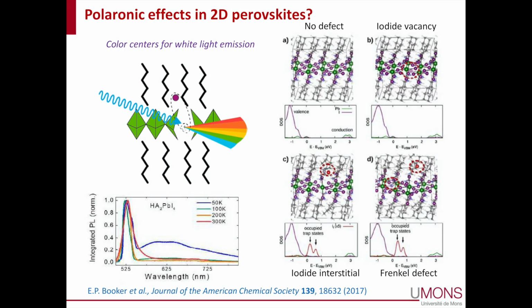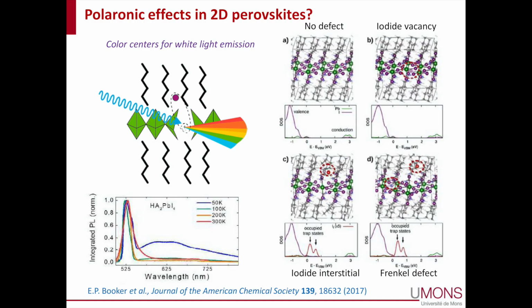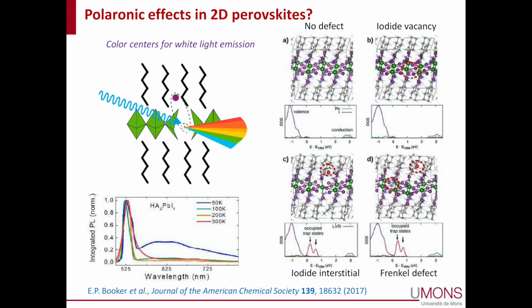clear fashion. Now, we have to be very careful with literature data because often you can see from the emission of 2D perovskite like this one, this broad emission at a low energy that has been discussed to be of polaronic nature. One of the other possible explanations that we put up together with the Cambridge group in this paper is that those emissions actually arise from color centers. I mean, ion migration is very easy in those materials, so you can have formation of, for instance, an iodine vacancy, iodine interstitial pair that will create trap states in the middle of the gap, and those trap states, we believe, are responsible for this emission. So you have to be very careful.